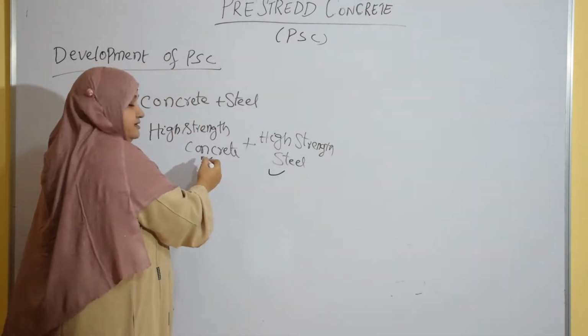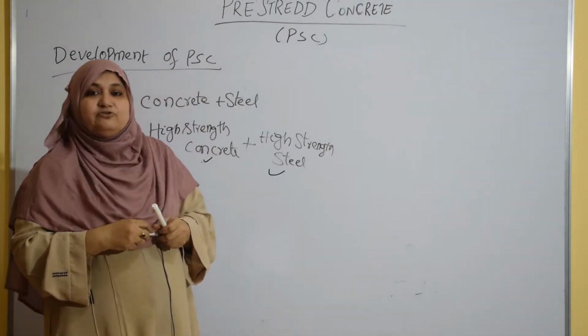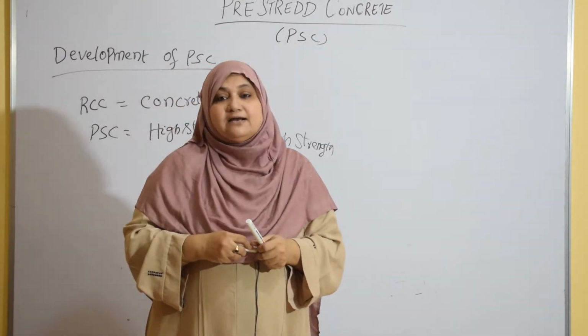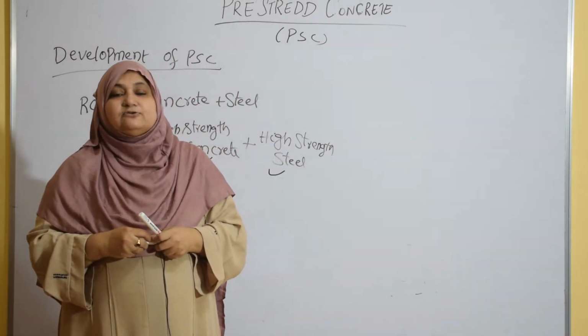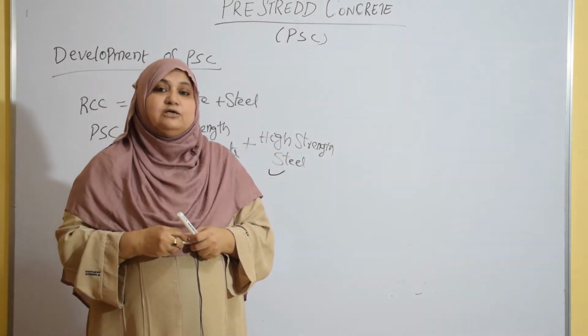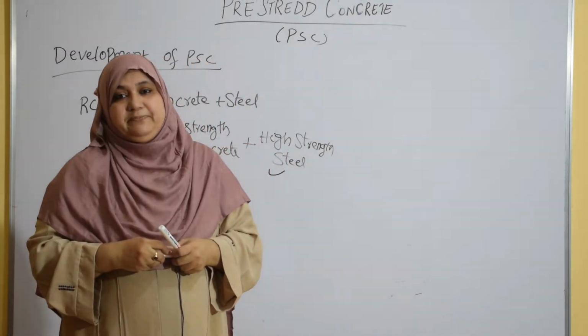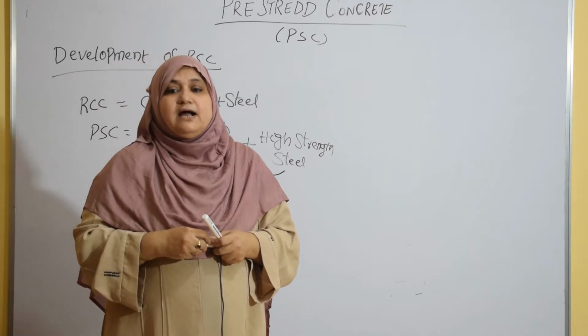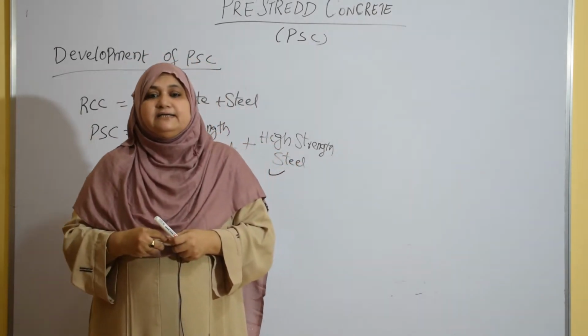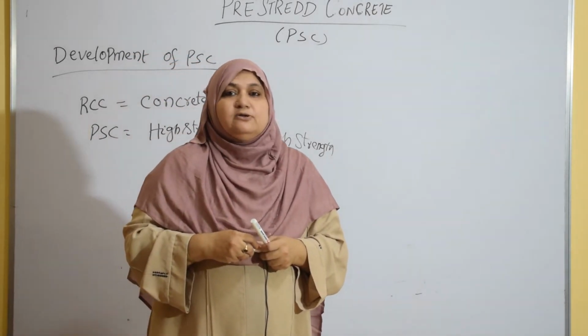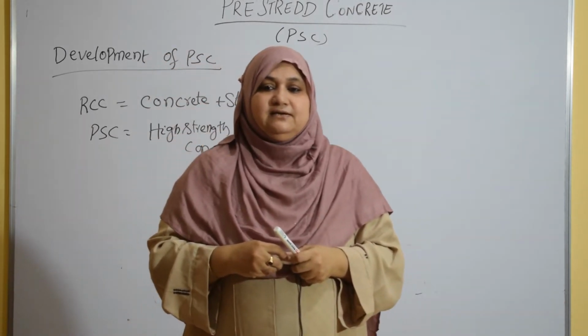Talking about concrete, it is less liable to shrinkage cracks at early stages, and it also has a lower modulus of elasticity and smaller ultimate creep strain, resulting in a smaller loss in pre-stressing steel, right?